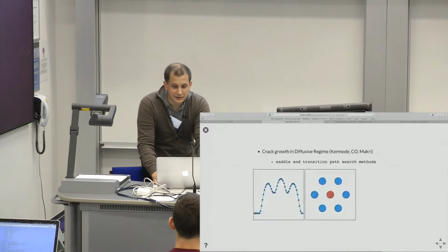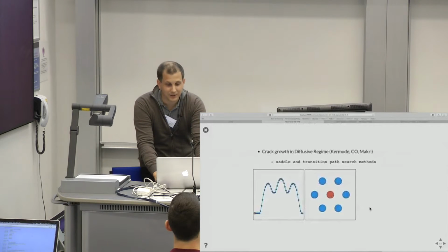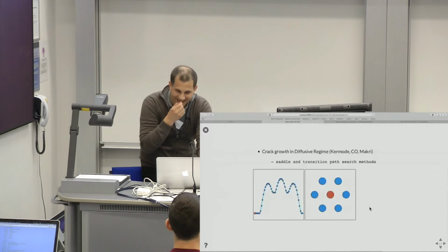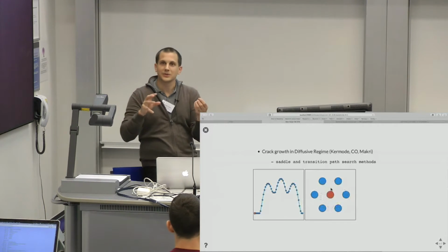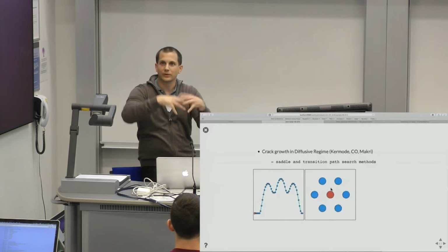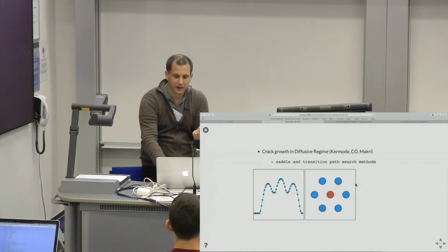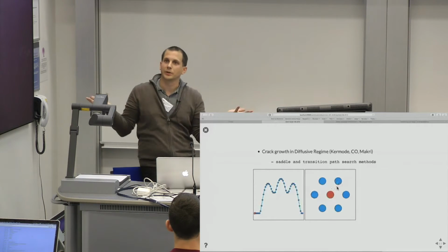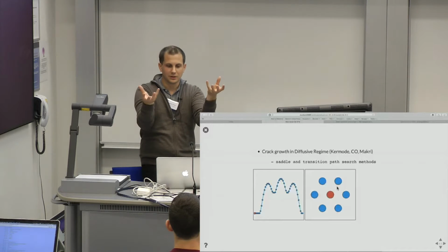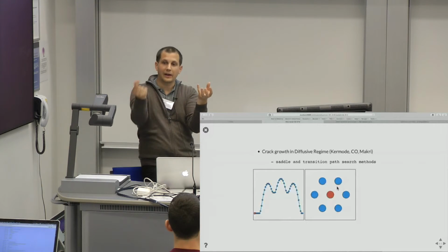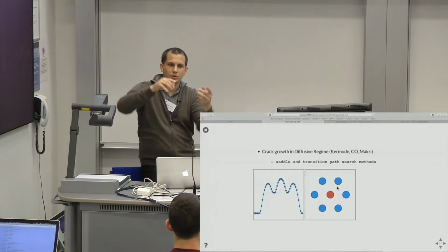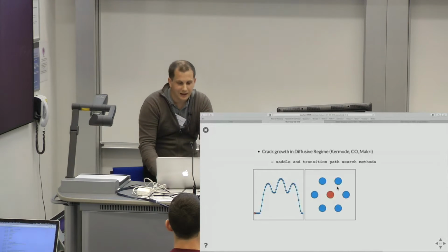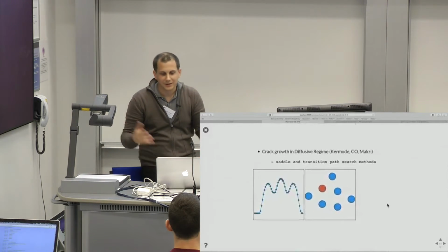All right. One of the things we've been working on is saddle search. I just put this in because I had some fun playing with Plots.jl, and so what happens in saddle search, this is a toy model, it's not a real problem. You put 7 atoms in the plane, so they're not allowed to move out of the plane. But you can see if I take 2 atoms and swap positions, then it's the same configuration again. And so you have 2 minima in the energy landscape, and now you want to find a path between them that's somehow optimal. Right? So you don't want to go over maxima, you want to go through the saddles on this path.